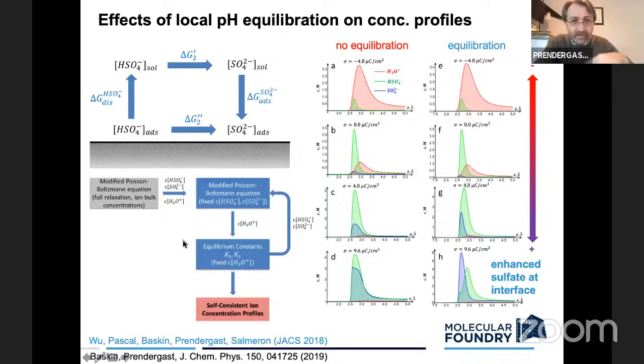And that should be calculated self-consistently, so that now, assuming that the equilibrium constants for proton addition and removal are the same as they are in the bulk, I don't know that for sure, but we've assumed that, then if you use that, you can come up with self-consistent charge distributions that deal with the detailed balance between the sharing of protons of these species. So if you don't include equilibration, as you go from negative surface charge through zero to positive and even more positive, you find that, yes, there is some sulfate at the interface in blue here, but there is always bisulfate. And it's only when you include this equilibration with the proton population, so allowing the pH to vary as a function of space, then you find that now sulfate begins to dominate the species at the interface.